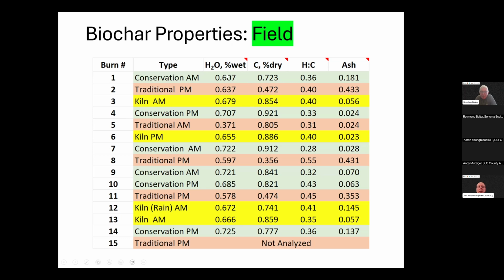Not only did we collect moisture content in the lab, but also carbon content, hydrogen to carbon ratio in the biochar, and then the ash content. And I think one thing you'll notice is the traditional burns have a much higher ash content than the other two biochars.